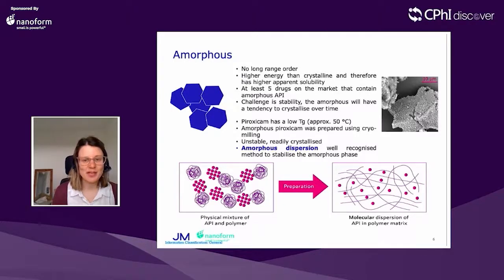A very common way to overcome this issue is to generate an amorphous dispersion. An amorphous dispersion is a solid solution of an API in a polymer matrix. So it's a molecular dispersion. What this means is that the amorphous phase is kinetically trapped. By having the molecule's presence in a polymer matrix, there's a large kinetic barrier to crystallization. There are a number of different pharmaceutically acceptable polymers that can be used for amorphous dispersion formation, and these can also be used to fine-tune the dissolution profile of the resultant amorphous dispersion.